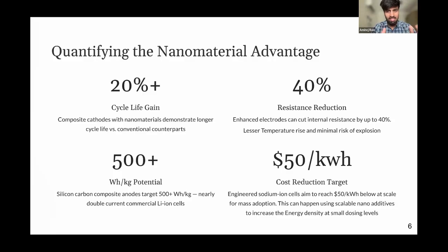We also aim for resistance reduction by 40%. And why is this important? Again, to stop thermal runaways inside batteries, we need to minimize the risk of explosion, and we need to keep the temperature on the lower end. So we need materials and electrodes that reduce the internal resistance of the battery. And it's a very simple test, which we call electrochemical impedance spectroscopy, through which we understand the charge transfer resistance and all the resistance inside the electrode.